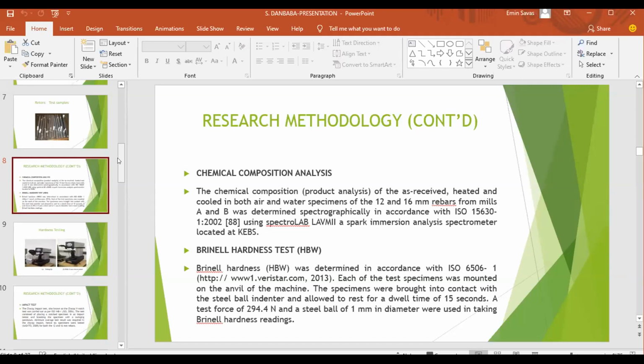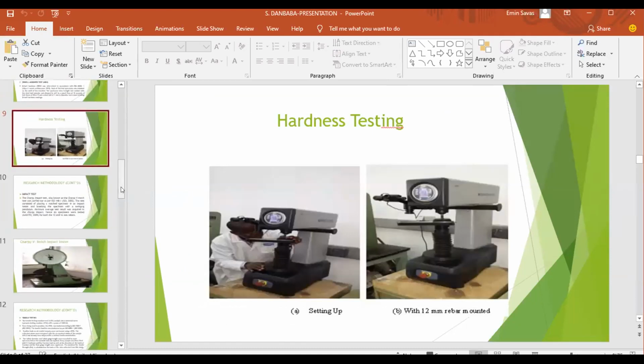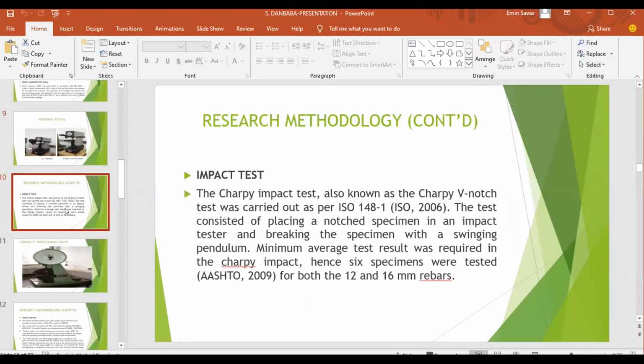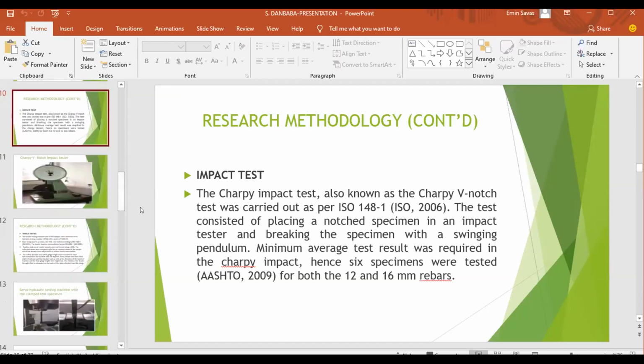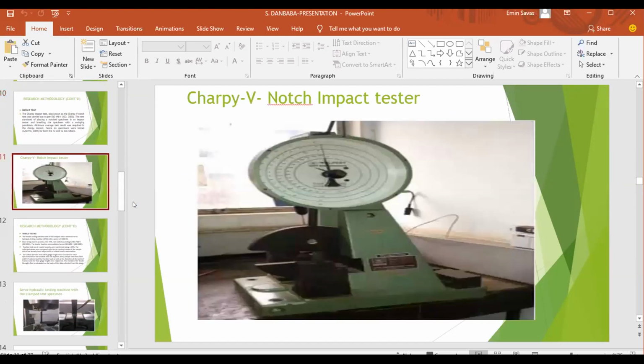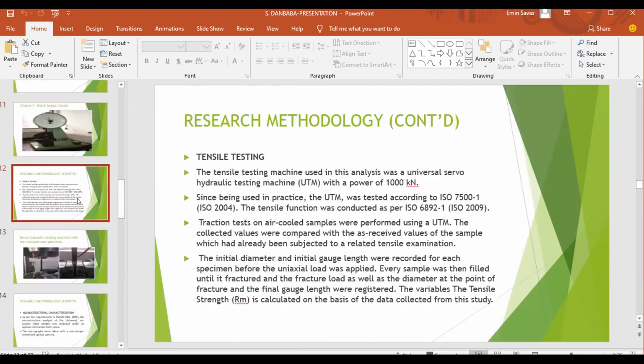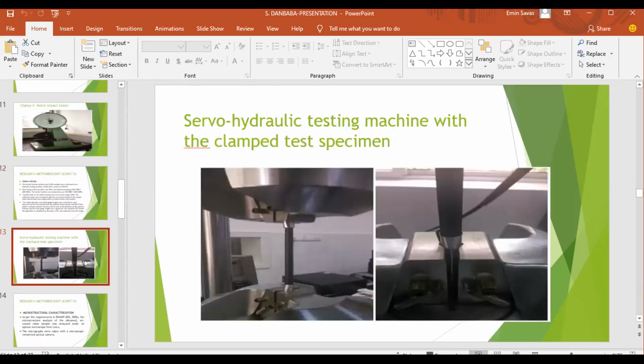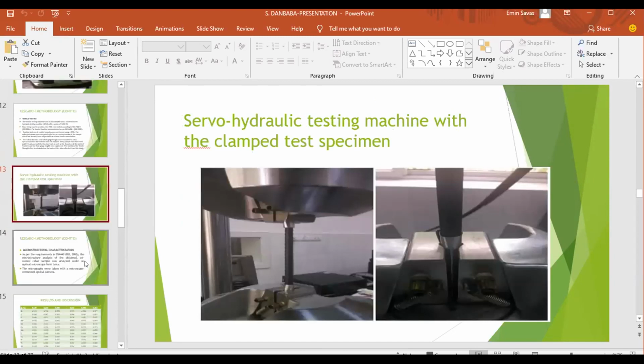So chemical analysis is important to start with, and you should check whether it is in accordance with the standard or not. So the chemical analysis was done. Then hardness testing of these bars was also carried out. Impact tests were also done, following the International Organization for Standardization standard. And here is a photo of the impact tester. Tensile testing is also done following the ISO standard, and this is the tensile testing machine.